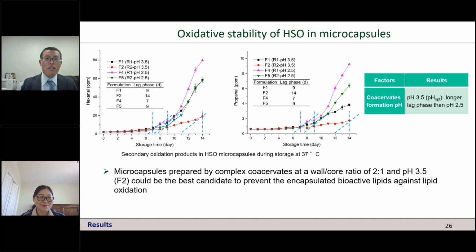Yeah, thank you. This question is very interesting. Of course, at the very beginning, I planned to study this project using the commercialized PPI, and we found, as in the picture I attached, the low solubility. That was a really big trouble for this study. So you ask me what about my result using the commercialized PPI? I would say I could not start my study because the concentration is very low. The sample that I requested from the company has around 0.1 weight percentage solubility.